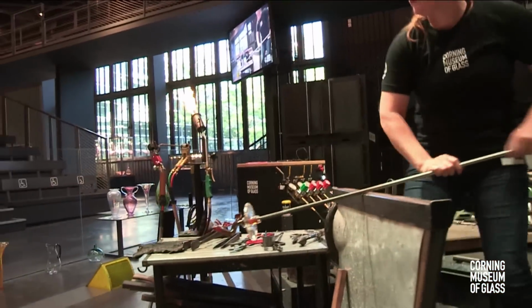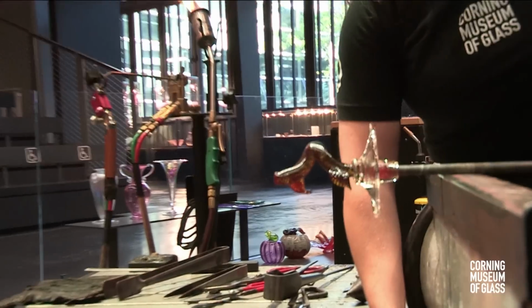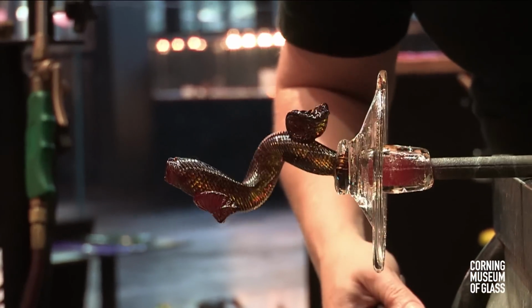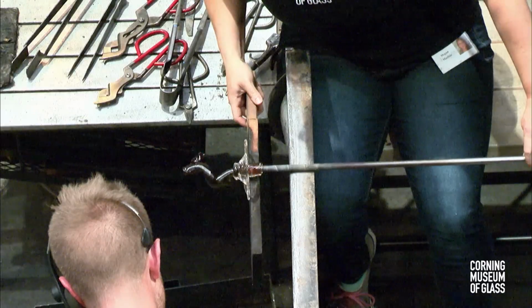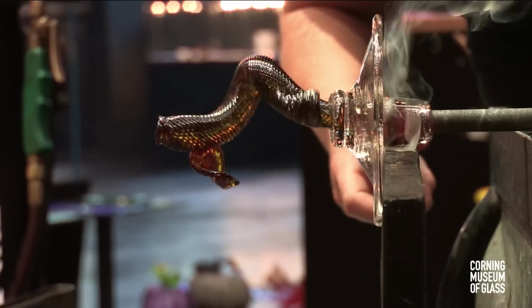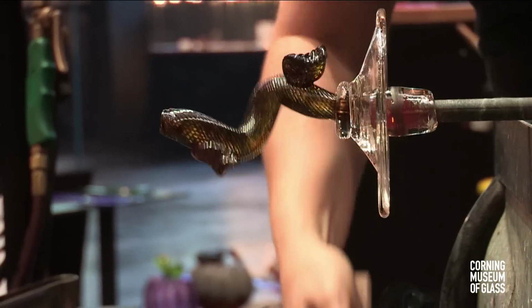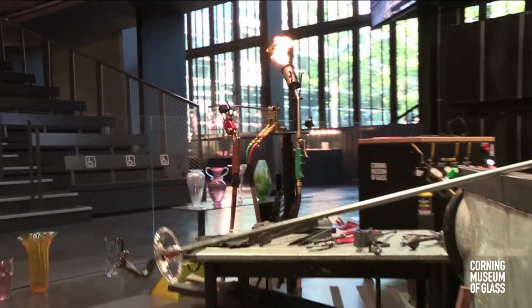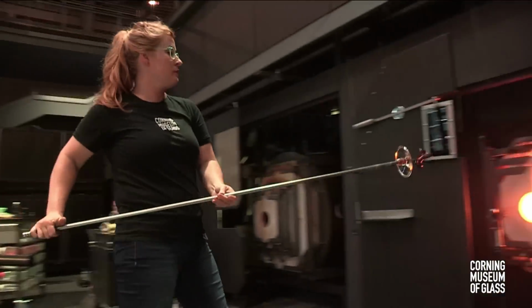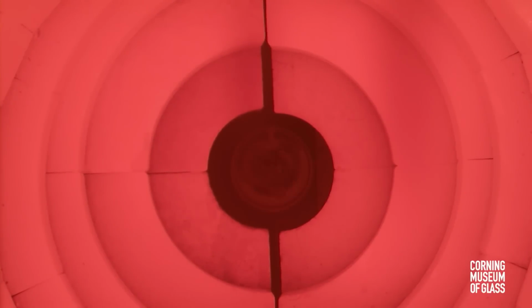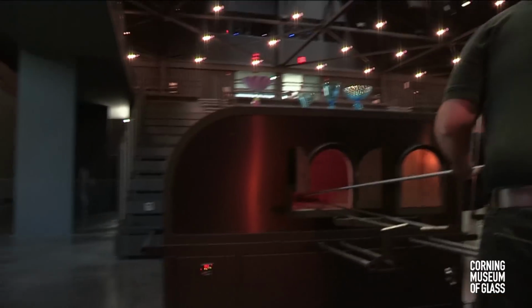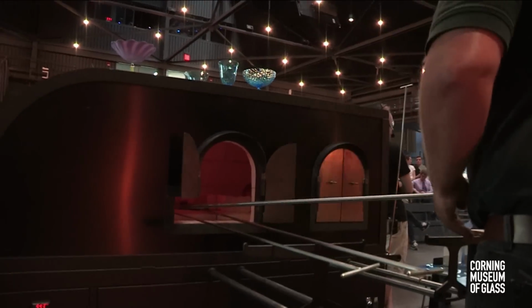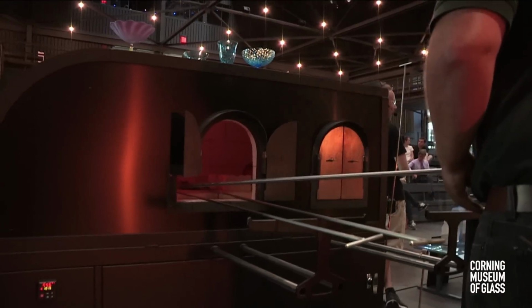You can see a little bit of that red glow has come back into the stem after that little reheat. And that's a good sign. The stem isn't really moving right now, but that slight orange tint that's in it is sort of a safety blanket, if you will, because that tells us there's enough heat and it's not in danger of cracking. Especially the foot. It might be hard to see from back there, but that clear foot has still sort of a yellowish tint to it, which is the heat, and that again is a nice little safety net. If that foot ever started to look like ice, basically no color to it, completely crystal clear, that's when you're getting into the trouble zone where the glass is going to get too cold on you and crack.